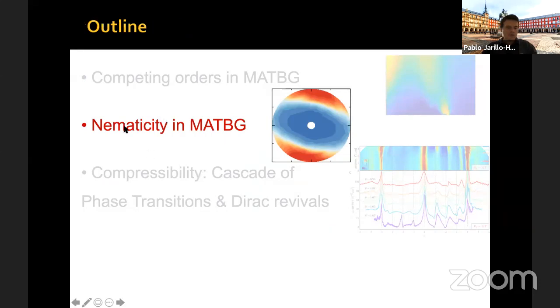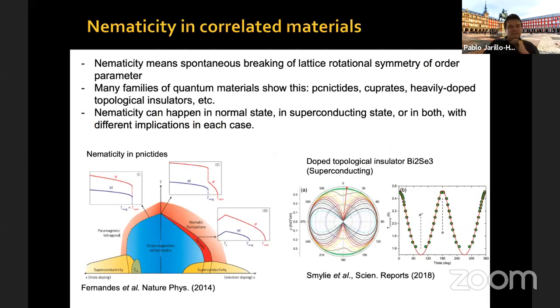So now let me switch gears a little bit and tell you about our observation of nematicity. Nematicity in correlated materials means spontaneous breaking of lattice rotational symmetry by some order parameter. Your lattice has a certain symmetry, for example 4-fold, 6-fold, or 3-fold, and a nematic transition indicates that your system now chooses a direction. It goes from whatever symmetry to 2-fold symmetry because it chooses a direction.